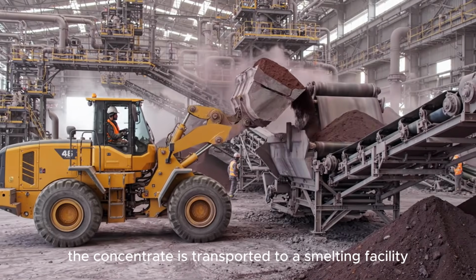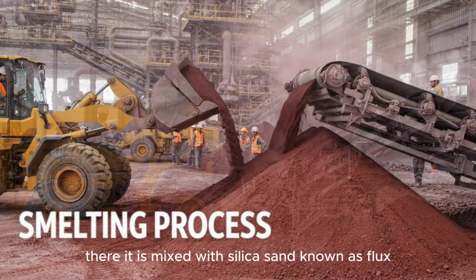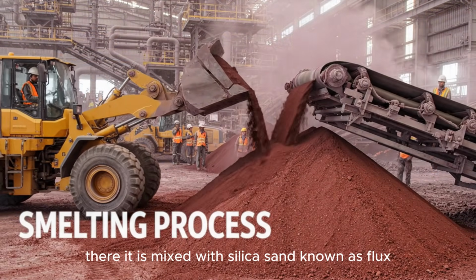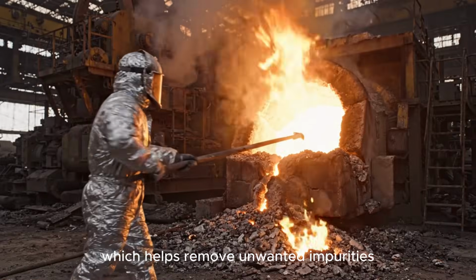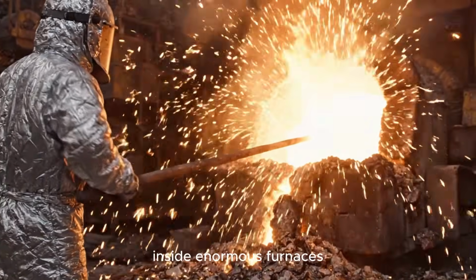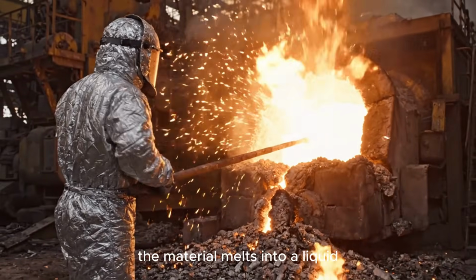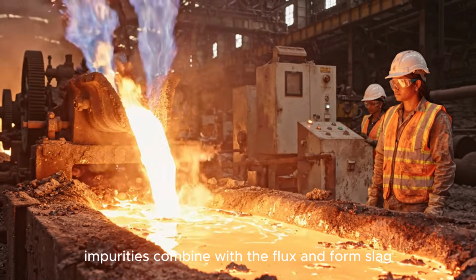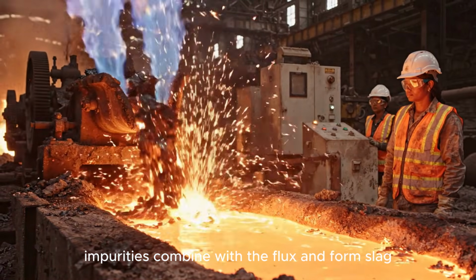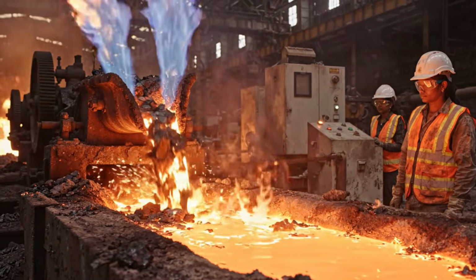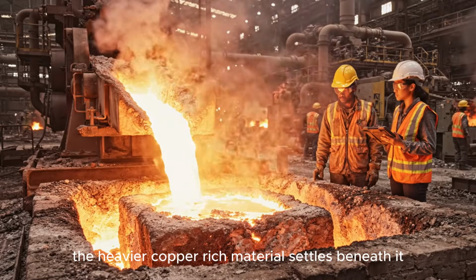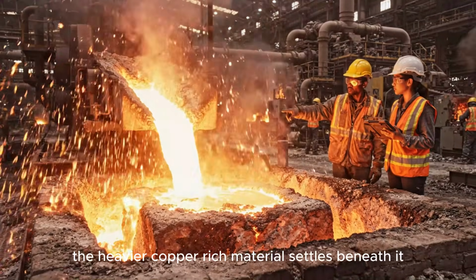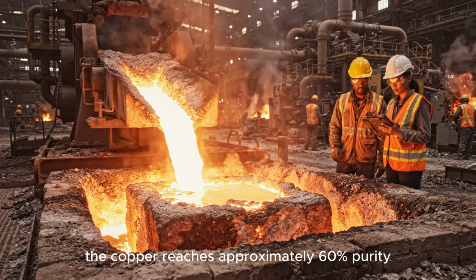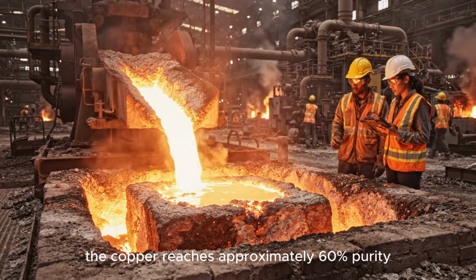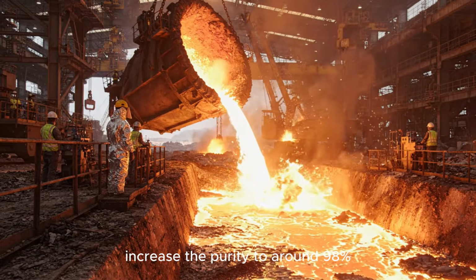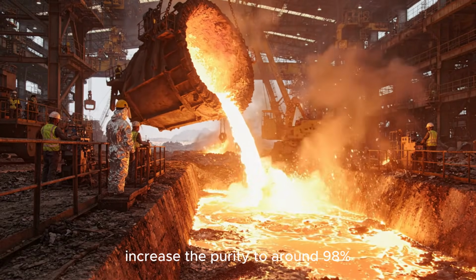The concentrate is transported to a smelting facility. There, it is mixed with silica sand, known as flux, which helps remove unwanted impurities. Inside enormous furnaces operating at extreme temperatures, the material melts into a liquid. Impurities combine with the flux and form slag, which floats on top. The heavier copper-rich material settles beneath it. At this stage, the copper reaches approximately 60% purity. Further smelting and refining increase the purity to around 98%.